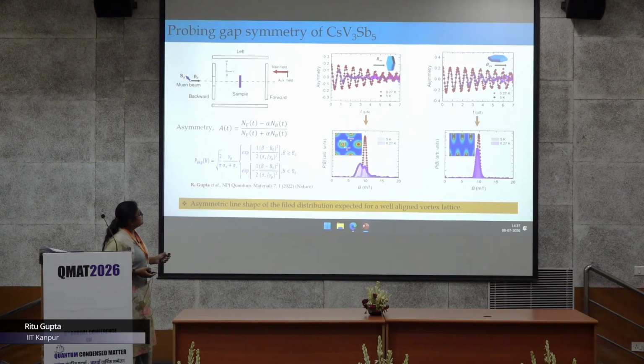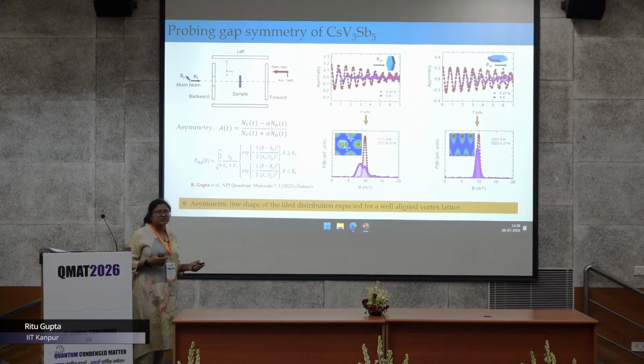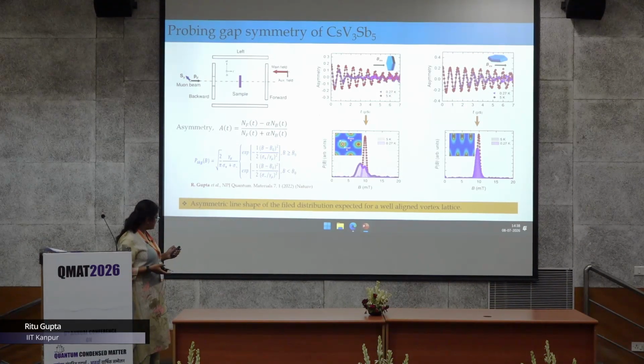One, we applied the magnetic field perpendicular to the Kagome plane, and the second, we applied the magnetic field parallel to the Kagome plane. I have shown this spectra for two temperatures, 5K, which is well above the transition temperature, and then deep inside the superconducting state, which is 270 millikelvin. So you can see in this spectra the damping is less. There is a slight damped signal. This is because of the nuclear magnetic moment present in the system. And then further, if you look at 0.27K, it is very much damped.